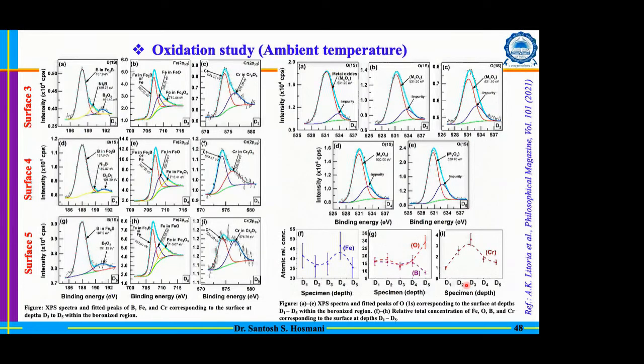So I will not explain this in much detail, just the last figure on the right-hand side, the bottom one. Here you can see the relative distribution of elements. What it says is, as we move into the interior of the material, that means we have removed more and more layers, from D1 to D5, you have a greater fraction of matrix. That is reflected in a reduction in the relative boron content. Your oxygen level at the surface increases.